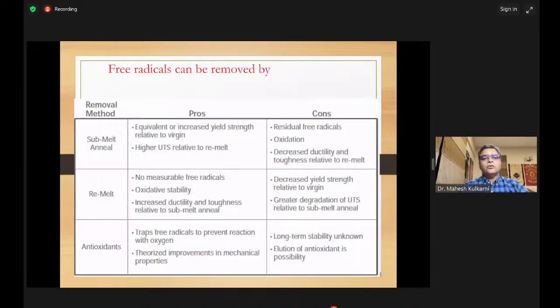So what can you do to remove these free radicals? You subjected the polythene to irradiation, you created cross-linking, but we have created some free radicals as well. Now, if you leave these free radicals, they are going to oxidize and create problems. So the polythene that we use will have one of the three methods that we're going to talk about, which will take away these free radicals, not completely, but to a great extent. The first method that we need to understand is annealing or submelting.